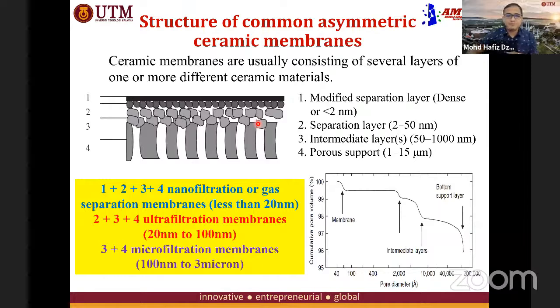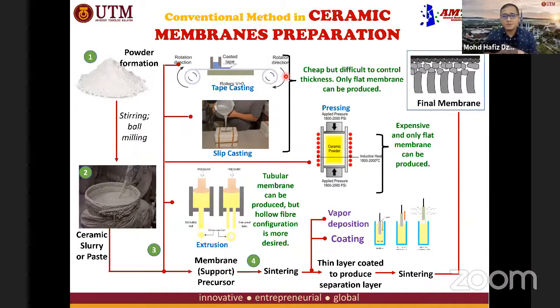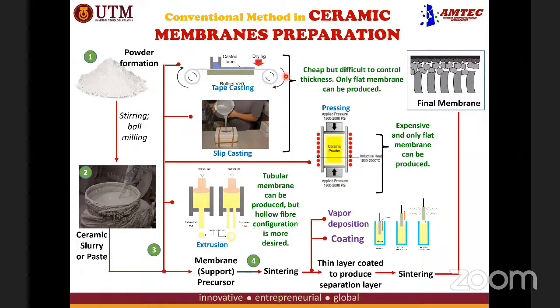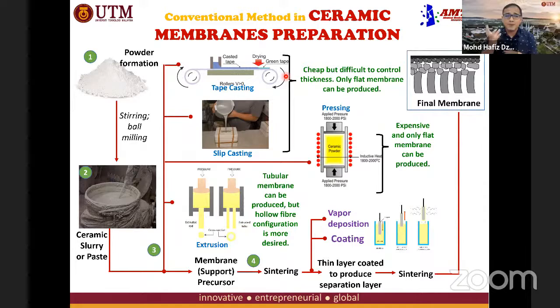So the conventional way to prepare the ceramic membrane is by using a multiple step process like this one. We have the powder mixed with some solvent, and we stir and ball mill to produce the ceramic slurry and paste. After that, we can produce the support precursor. How to produce the support is either by using tape casting, slip casting, or pressing. This is to produce a flat sheet membrane. Flat sheet membrane means that it's like a planar membrane.